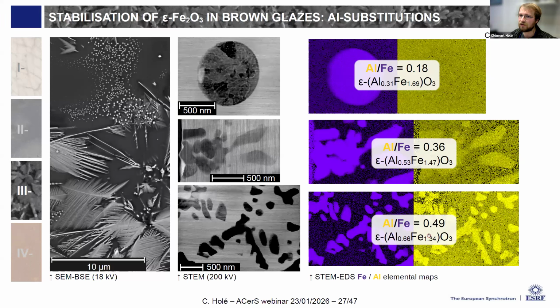So it means that the iron epsilon oxide inside brown glazes is not really iron epsilon oxide, but in fact a solid solution, or a heavily aluminum-substituted phase, between this mixed oxide and pure iron epsilon oxide. And knowing this, we suppose that aluminum is actually helping this structure to grow to such enormous phases compared to the nano size that is usually confined with the nanoparticles.